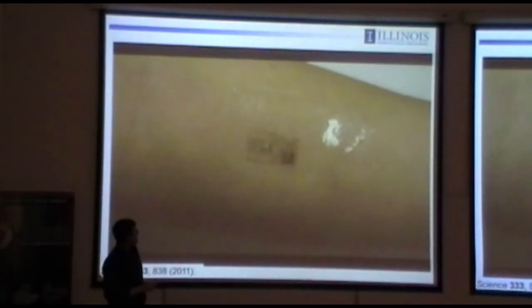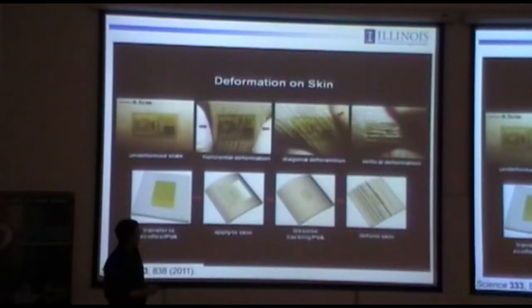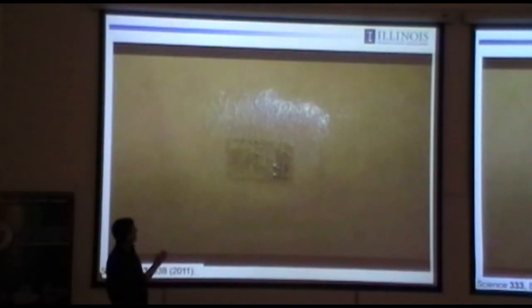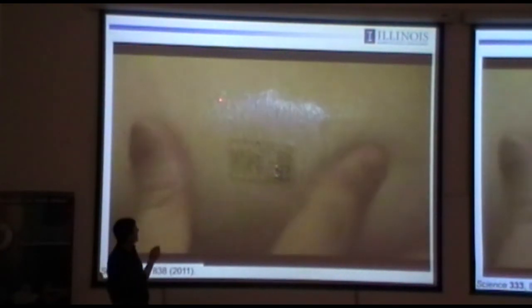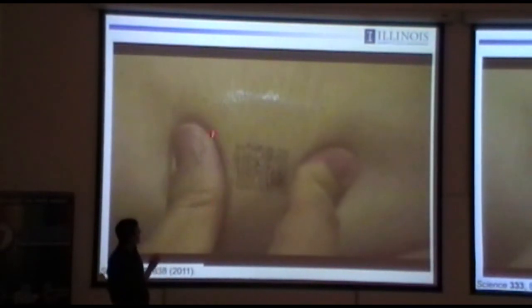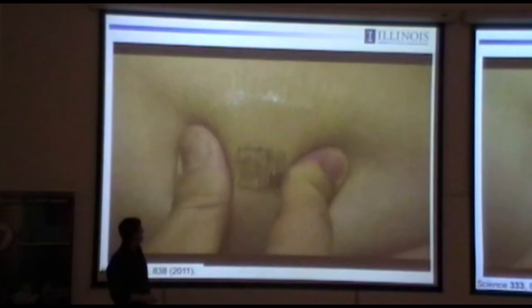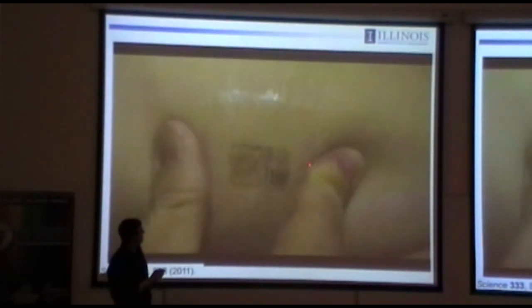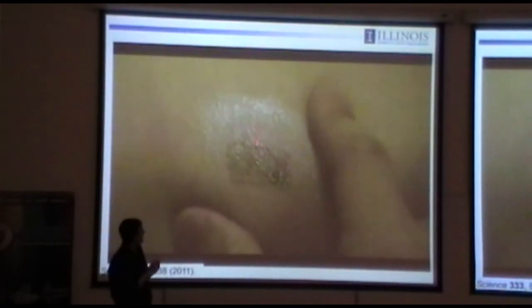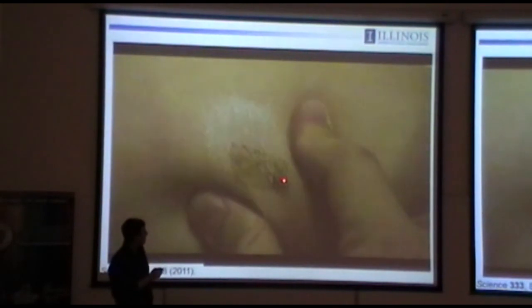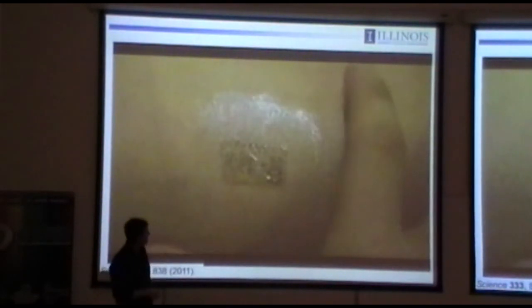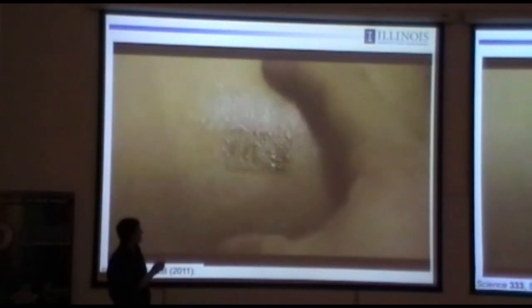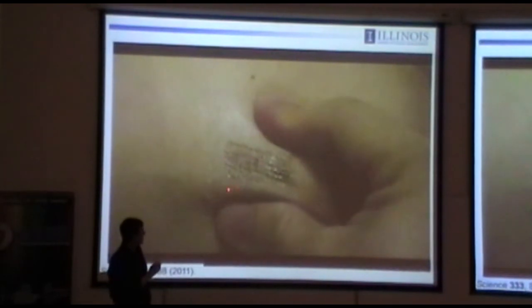So the PVA is gone, you can dry it off, and we'll come back, and you can pinch the skin and now watch the mechanics of this integrated piece of electronics on the skin. So this electronic, you're looking through the silicone sheet. This is the boundary of that silicone substrate. So again, 30 microns in thickness, 50 kilopascals roughly. And as you pinch and deform the skin, you will notice that the skin wrinkles and deforms in ways away from the circuit that are almost indistinguishable from the way that it deforms where the circuit is located. In particular, look at the period of those wrinkle structures that appear upon compressive stress associated with pinching. It looks pretty much the same at the circuit as it does away from the circuit.